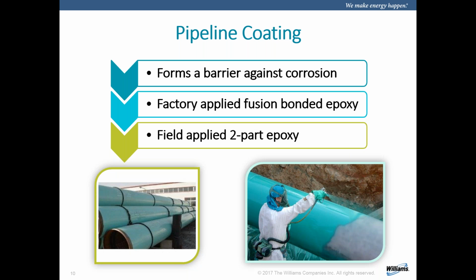So we do have a couple of forms of coating. Obviously, I've mentioned before, most cases now it comes out of the pipe mill already with coating on it through a fusion bonded epoxy, which is a really strong epoxy that prevents the corrosion. And then also it is applied in the field as a two-part epoxy for enhancement. You'll notice that in the lower left corner of that slide, the factory applied coating is already on that pipeline. It's typically a green coating for the fusion bonded epoxy, and then the weld areas are not coated. Those get coated in the field after the welding is done. And so in the photograph on the right, you'll see a gentleman who is applying a two-part epoxy in the field. So coating is an important factor of pipeline safety. There's no question. It prevents corrosion from our pipeline.